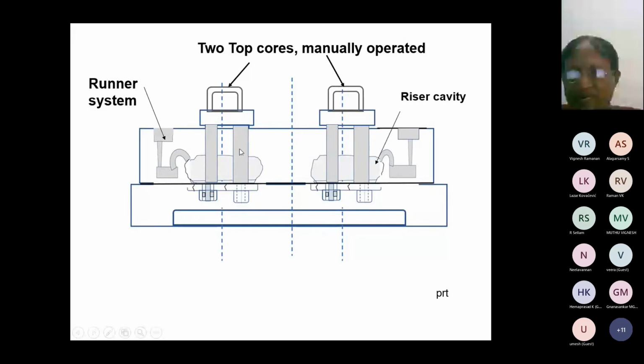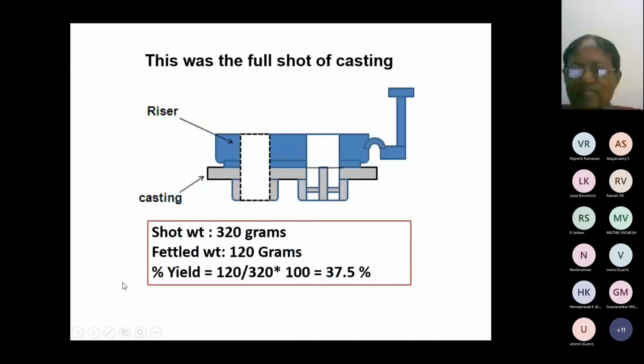These are all two cores. These are all manually lifted cores, each weighing about 5 kilos, and the casting has got to be removed. There is no ejection at all. The operator has got to lift the core every time, which is about 200 degrees centigrade, and then lever the casting out and take out the castings. Very strenuous one. Operators were afraid of operating this die. And this was the full shot of the casting removed from this die.